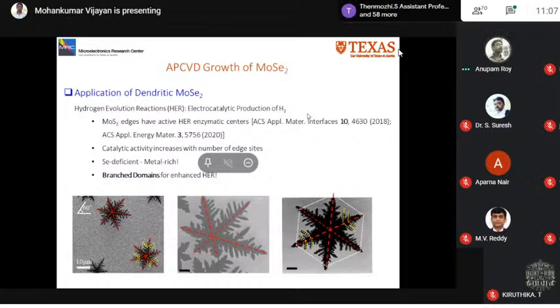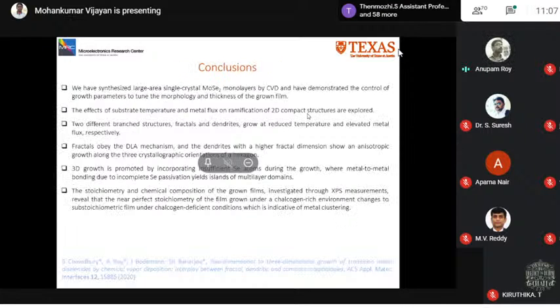So in the conclusion, here I showed that we can synthesize large area single crystal MoSe2 monolayers using CVD, and we have demonstrated the control of growth parameters to tune the morphology and thickness of the grown film. The effects of substrate temperature and the metal flux on ramification of 2D compact structures are explored. Two different branch structures, fractals and dendrites, grow at reduced temperature and elevated metal flux, respectively. Fractals obey the DLA mechanism, and the dendrites with a higher fractal dimension show an anisotropic growth along the three crystallographic orientations of a hexagon.